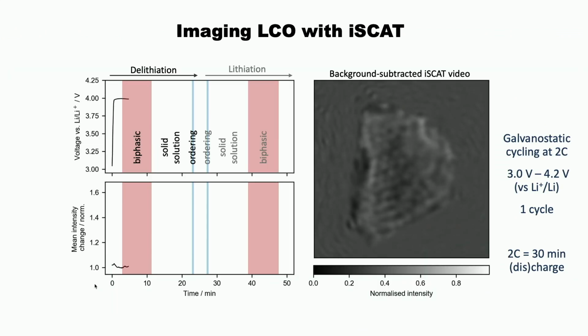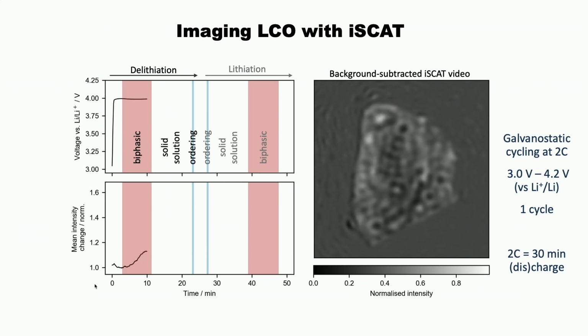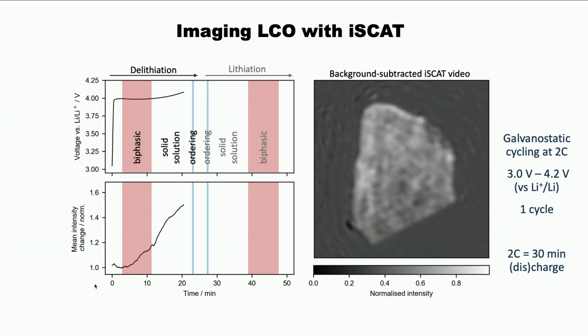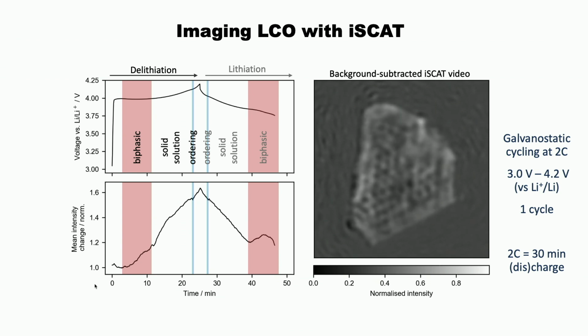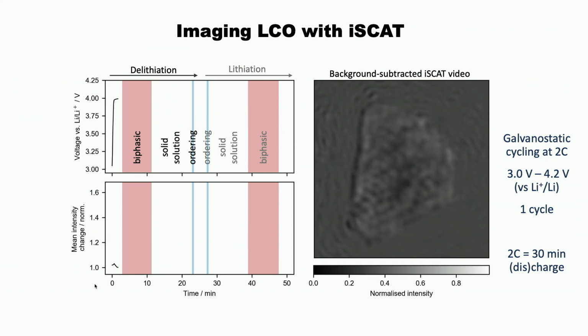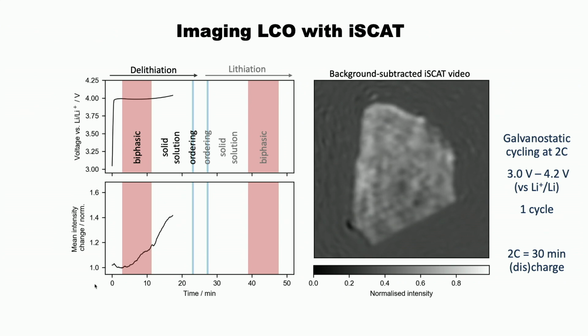And then we got this image in March 2020, and we had all of the pandemic to work out what was going on. So this was the one positive for the pandemic for me, was that we could actually think about it. So what you're watching is, this is now lithiation. That's the Li 0.5 phase transition. This is a solid solution. And this is the two-phase reaction. You're going to see a nucleation across there. But now watch it in the other direction. So we're going to start with a fully lithiated particle, and you're going to see that actually things start to emerge from the edges and you come shrinking in. And then you have a solid solution. And then this thing coming up here is the ordering transition at Li 0.5, ripping through this particle.